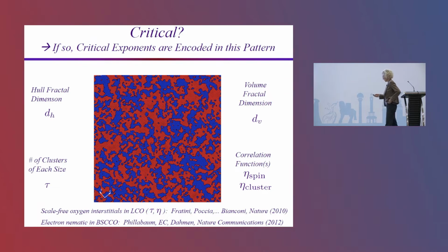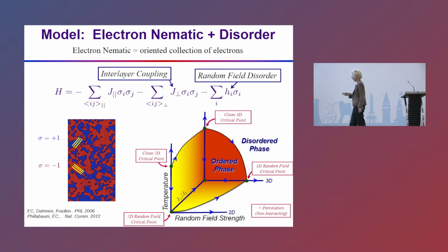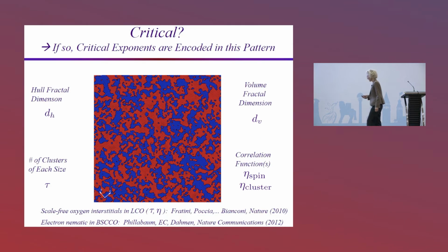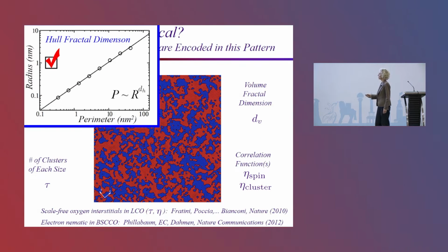So what can we get out? We can get out the Hull fractal dimension. So this is the question of these boundaries. How lacy are these boundaries? And when we analyze that, we would be looking at the radius of gyration of a cluster versus its perimeter. When plotted on a log-log scale, it's nicely linear. This is out of the data. And so we have more than two decades of scaling, so we're confident in our ability to extract this critical exponent.